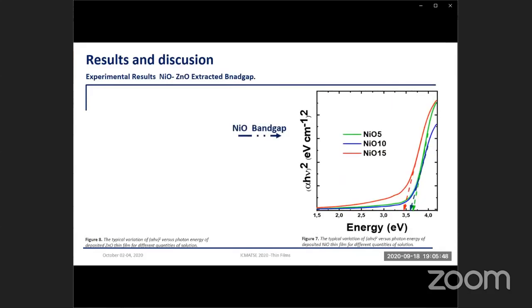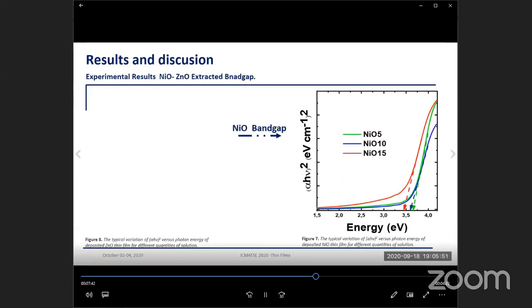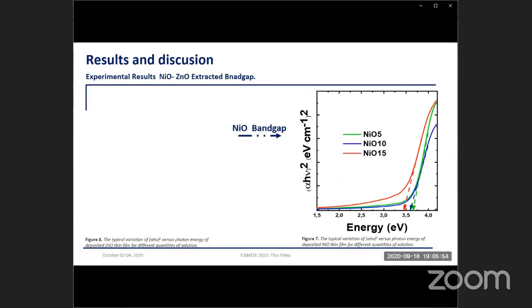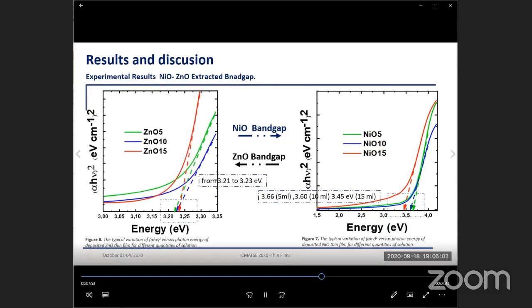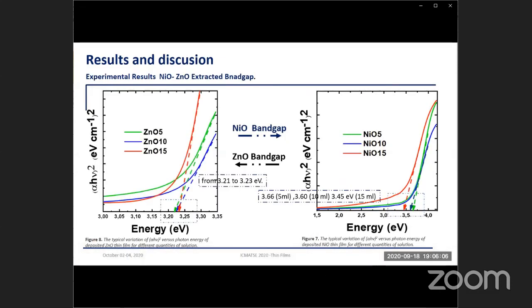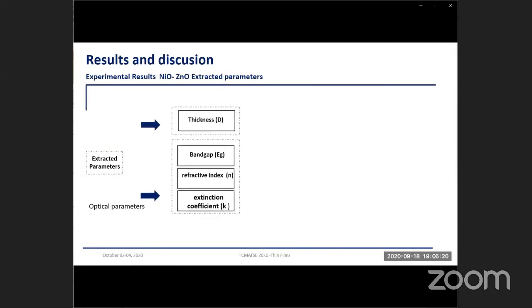As you see, the band gap of nickel oxide decreases as the quantity of solution increases, from 3.6 to 3.5 electron volt. For the zinc oxide films, as the quantity of solution increases, there is a negligible increase of the optical band gap. The extracted parameters of nickel oxide and zinc oxide thin films used in simulation are thickness and optical parameters, as we said: band gap, refractive index, and extinction coefficient for all deposited thin films.